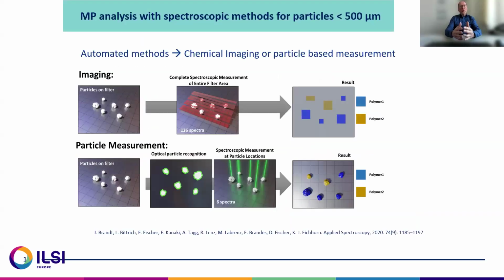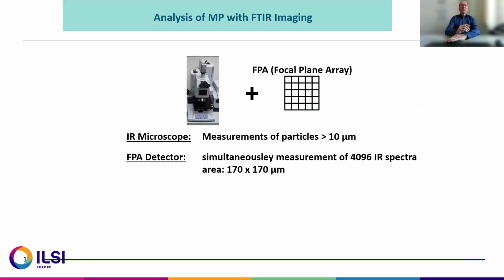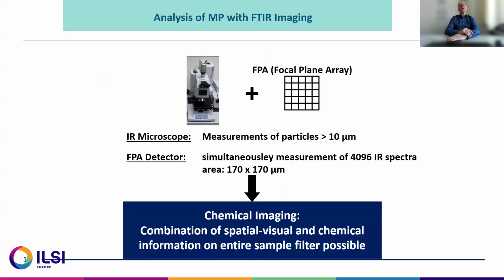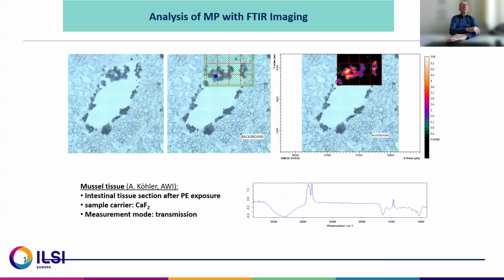In principle, if you use spectroscopic methods for particles below 500 microns, you can use a chemical imaging or a particle-based measurement. Imaging is mostly used in FTIR because you can use a focal plane array detector, and the particle measurement is mostly used for Raman. For FTIR, as shown here very quickly, you have a focal plane array detector and you can simultaneously measure 4,000 spectra at the same time. This is a great advantage in time, but the disadvantage for FTIR is that you can only measure particles bigger than 10 microns.